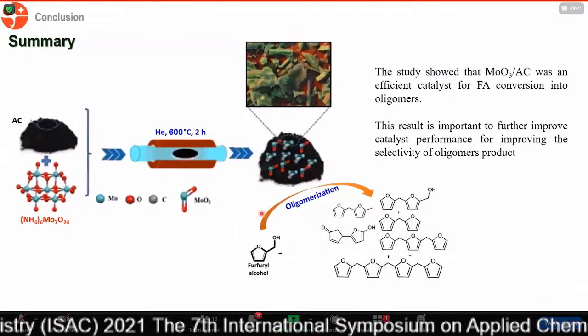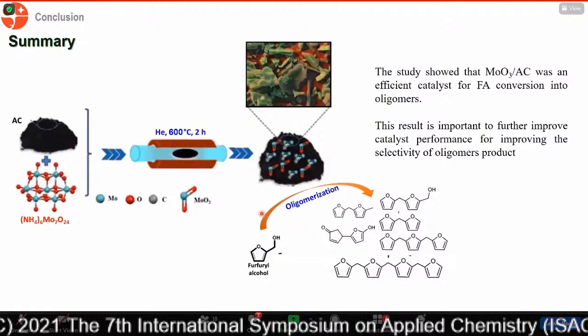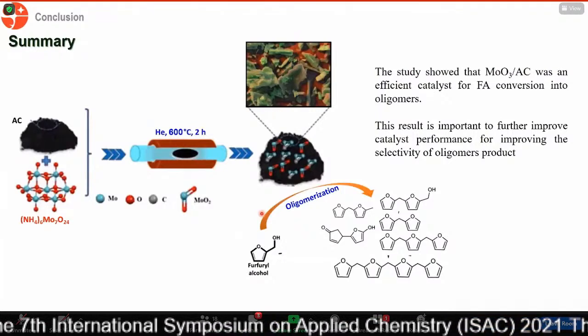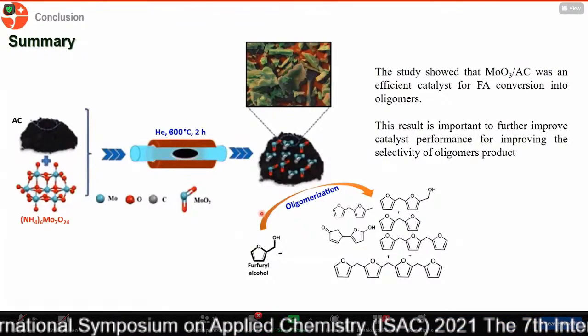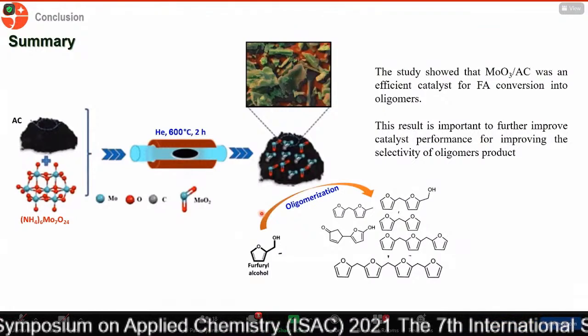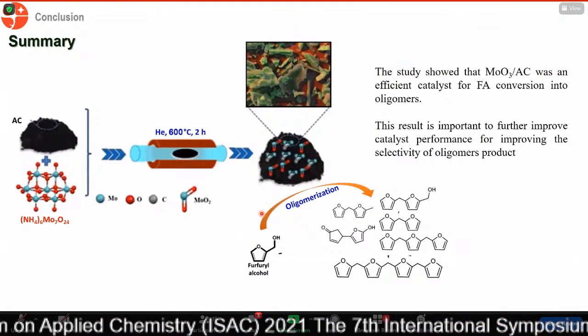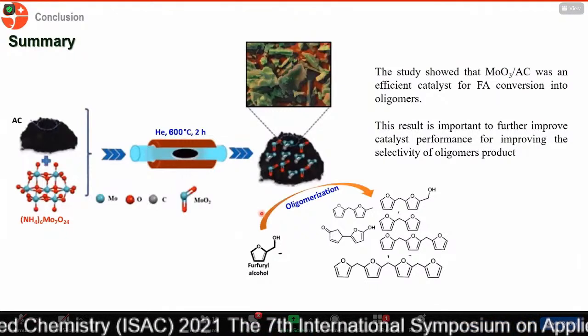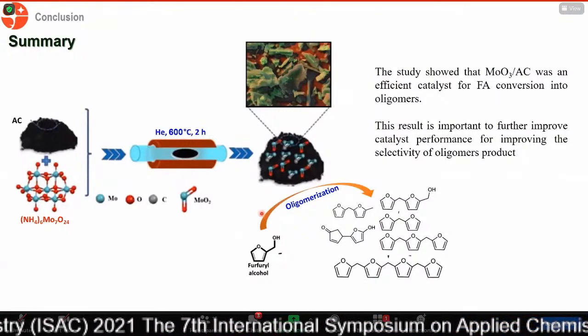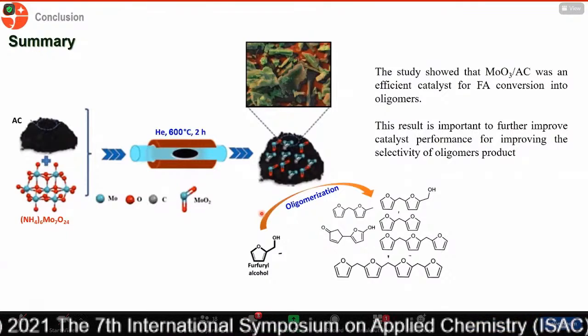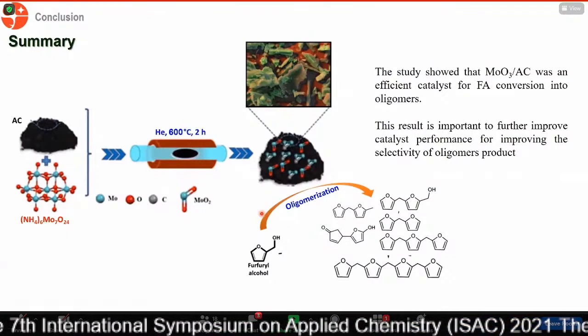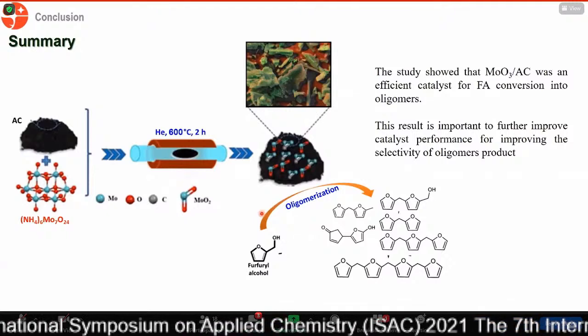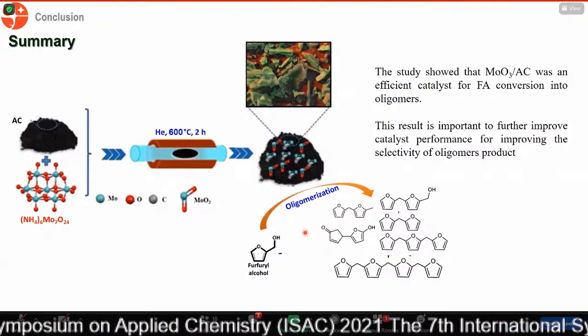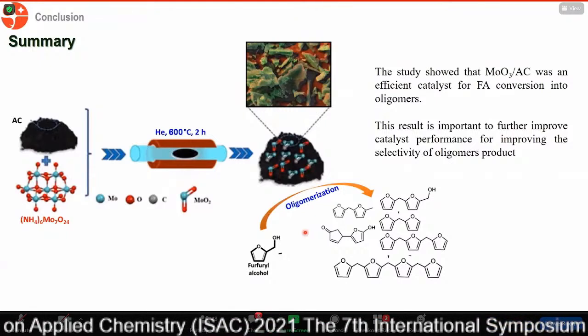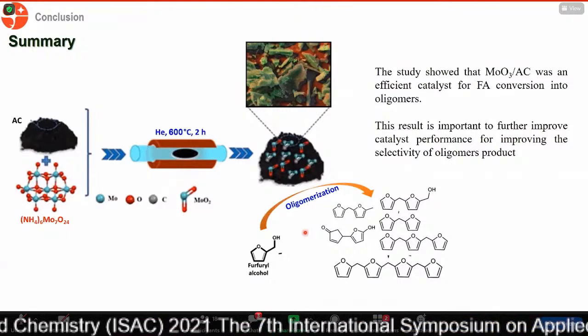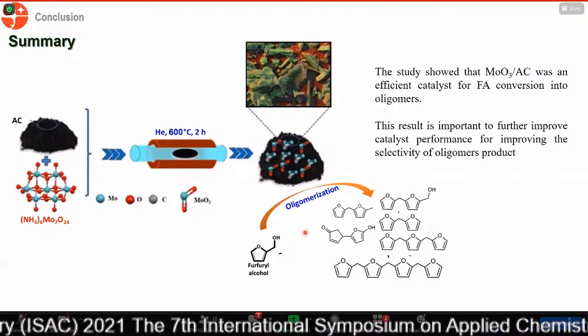And the last one, we have shown that molybdenum oxide on activated carbon was an efficient catalyst for furfuryl alcohol conversion into oligomers, which is specifically dimer and trimer. And this result, we believe that it is very important to further improve the catalyst performance for improving the selectivity towards dimer and trimer compounds, which are very useful for jet fuel precursors.